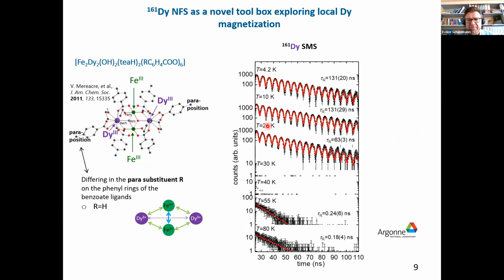Of course, when you heat the sample, you turn on relaxation, and these measurements can also be used to determine the relaxation rate of the dysprosium, as shown here, ranging from 130 nanoseconds at 4.2 K, still static here at 10 K, but then highly dynamic. And if you are in that regime, you don't measure anything in forward direction, and the signal comes back when you have the limit of fast relaxation of the dysprosium magnetization.